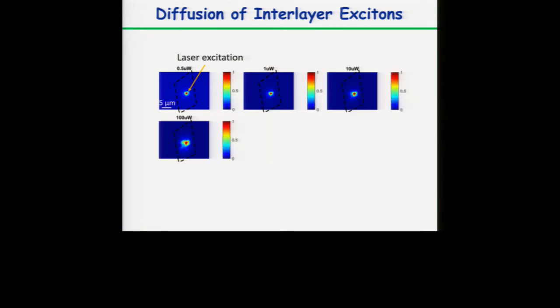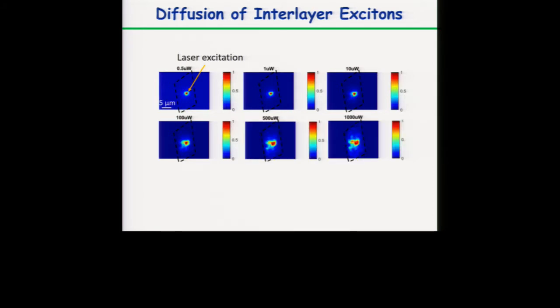But if we keep doing this process, for example now at 100 microwatts, we are collecting from a large area, and we are seeing that the spot looks bigger on this region. And if we keep increasing power to around 1 milliwatt, now it's hard to see here, but the whole sample gets illuminated. So we are generating interlayer excitons in the center, but because they are dipoles, they repel each other once you keep adding them with higher power.